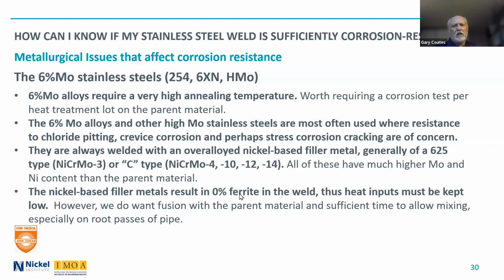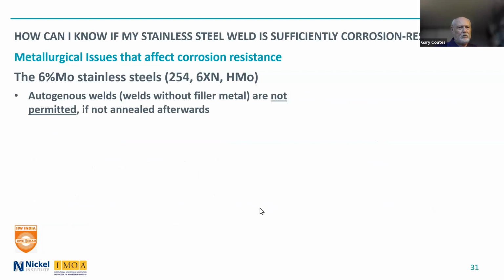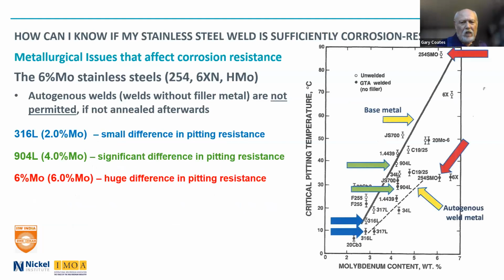Now, we want low heat input, but we want fusion with the parent material and sufficient time to allow mixing, especially this is important on the root passes of pipe. With 6% moly alloys, autogenous welds, and that's welds without filler metal, are not permitted unless they are annealed afterwards. So basically, autogenous welds are forbidden, and this chart shows what the effect is, and on the vertical axis is